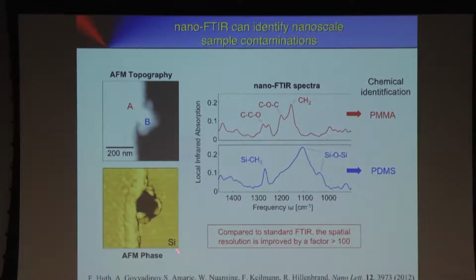And that's the atomic force microscopy phase image, which kind of gives us a mechanical map of the sample. And we see that this particle seems to be different. It seems to be neither PMMA nor silicon, so it's something different. And it's rather difficult to say from these atomic force microscopy images what it is. But now having infrared spectroscopy at hand, we can place the tip at A and B and record spectra. On A, we get, again, this PMMA spectrum. But on particle B, which is only 100 nanometer away, we get here completely different spectra with bands that we can associate with the PDMS.